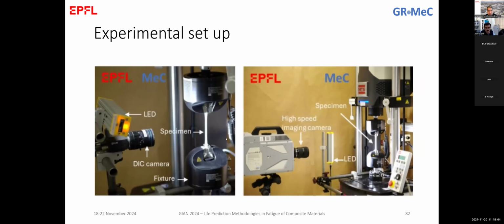So again, the setup is similar to what we had before, with the specimen mounted on the machine. This is a different machine. It's an electrodynamic machine. It's not a hydraulic machine. It's a new machine from MTS that can apply loads up to 3 kilonewton. So it's a small machine, but not with hydraulic pressure, with electrical motors. And again, here we use the DIC camera. We use the high-speed camera to take some photos of the specimen when it fails.